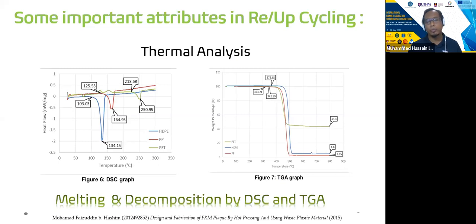This figure shows two graphs. The first one, figure 6, is a differential scanning calorimetry, showing different peaks representing different melting temperatures for different waste polymers. What you can see here, the blue curve indicates the high density polyethylene, which melts at a temperature of 134 degrees Celsius. And the polypropylene has a slightly higher melting temperature, around 165 degrees Celsius. And if you look at the PET, this one is a material from a mineral bottle. It has a very complex curve showing different melting of the materials when it is heated up to 400 degrees Celsius.